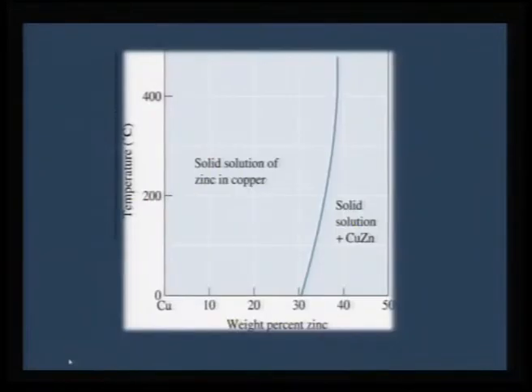So, this is what we see in this view graph. Solid solution of zinc in copper is possible only in this range, only in this range where the limiting composition is 30%. Beyond this, it is not a solid solution because it deviates from the FCC pattern of the parent copper. Whereas, above 30%, we cannot completely exclude the possibility of a solid solution. There is going to be solid solution plus some other alloy phase of copper and zinc.